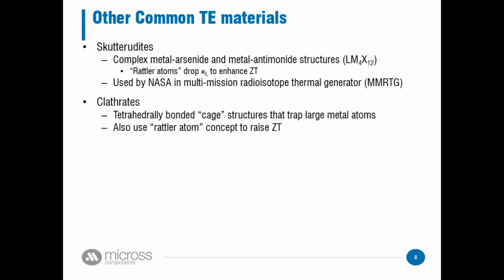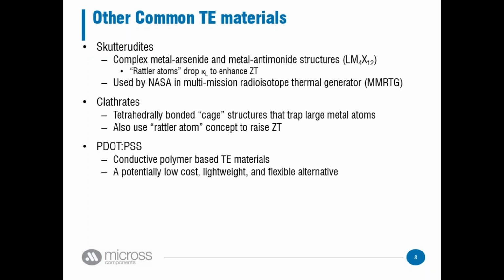Clathrates are another type of material you may hear about when you read about thermoelectrics. It's essentially a cage type structure. And again, it uses the same sort of rattler atom that we talked about with the skutterudites. Essentially the two different resonant frequencies of the materials cause a drop in thermal conductivity, which again gives you the high ZT. Another interesting group is the PEDOT:PSS group of materials. I'm not a polymer chemist, so I can't tell you too much about these or their crystal structure, but I know that they're a polymer.